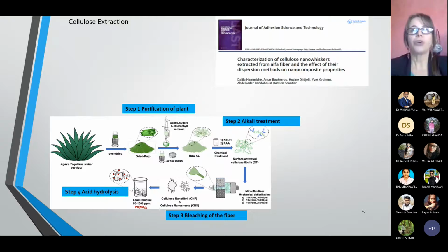Then we proceed to the third step. It is the bleaching of the fiber, because we have to obtain a white color of cellulose. And because of persistent coloration, the product is bleached with sodium chlorite mixed with glacial acetic acid mixture to remove any residual lignin and hemicellulose that may still be in solution. Bleaching treatment is carried out to bleach the fiber. Then it is filtered and washed with distilled water.